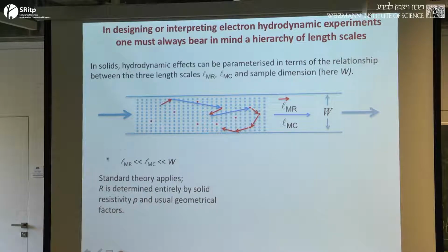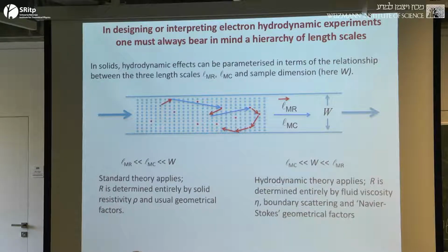If the momentum relaxing mean free path is the smallest length scale in your system, then you're in the standard regime where the resistivity or the resistance is calculable just by the properties of the material in the way that we, at least as solid state physicists, all grew up with. If, however, you can arrange somehow that the momentum conserving mean free path is the smallest length scale in the system, and if it's really, really the smallest length scale in the system, then you might start to be able to calculate your flow resistance using the viscosity as the dominant term in the Navier-Stokes equations.